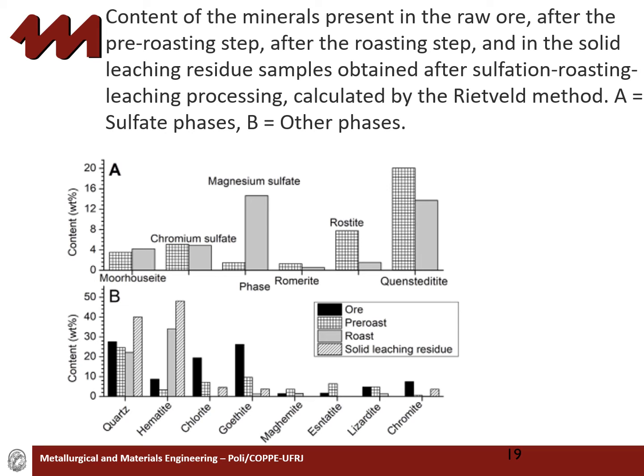There was a substantial increase in the amount of hematite, around 400%, in the residue when compared to the quantified in the raw ore sample. This results mainly due to the transformation of goethite to iron sulfate and their subsequent composition to hematite and the decomposition of non-reacted goethite. Furthermore, in the case of silicates, the acid attacks the structure of the phyllosilicates, breaking the bonds of the octahedral and tetrahedral layers, leading to the dissolution of the elements of the phase and transformation of also leachable amorphous silica. This attack explains the decrease in the amount of chlorite, indicating that this mineral reacted with sulfuric acid and/or the gas SO3 or decomposed during the thermal processing.